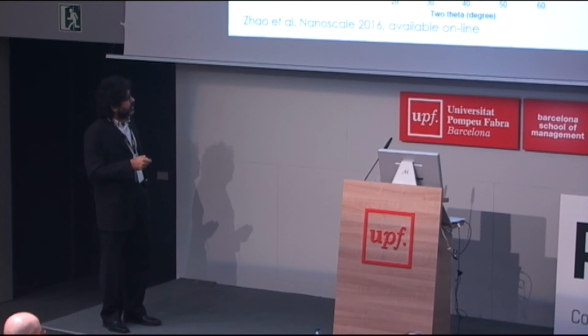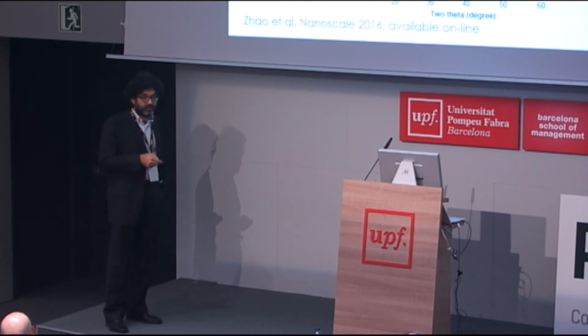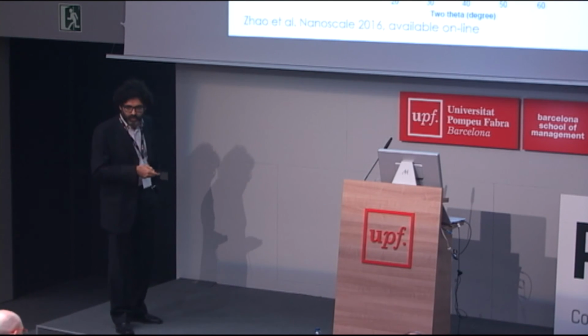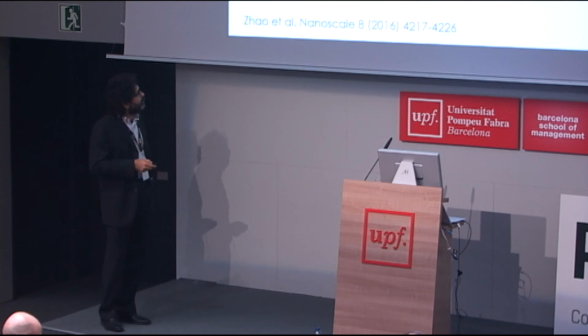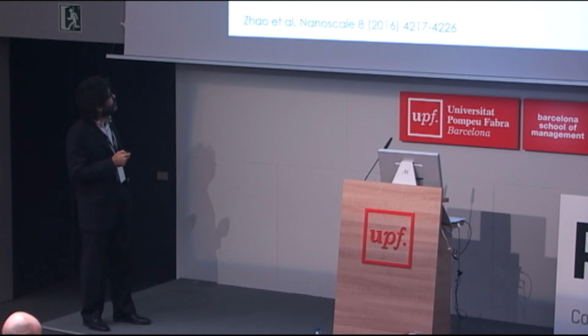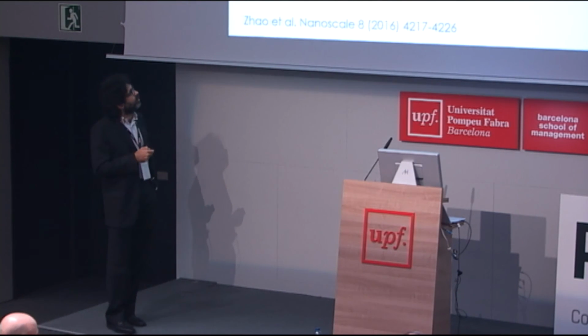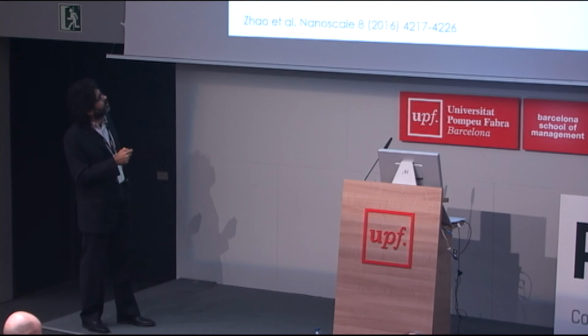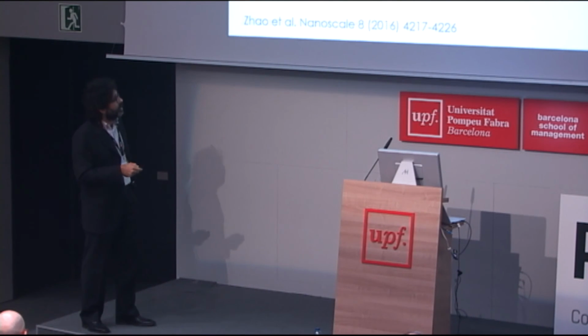Phase identification through XRD was almost impossible in the core shell system due to the overlap. So we tried to get some optical characterization of the system, as you can see here.